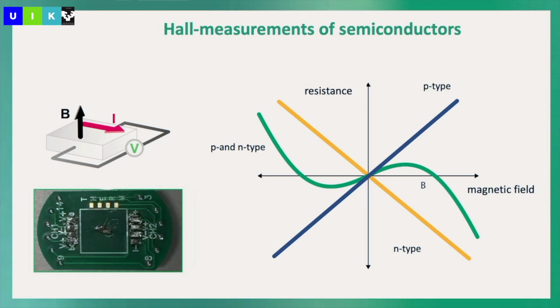This is what you can distinguish even in semiconductors, very typical. Then you can see what the charge carrier concentration is and so on from this measurement. But sometimes you also see wiggles here, and you might think it's impurities, but in these materials we very often see very nice quantum oscillations, from which we can even draw a conclusion by a simple transport measurement about what the electronic structure looks like. So we don't even need ARPES or photoemission or some complicated measurements, because very often we get this information. And it's amazing, before I never did this, but now, since there's topology, all my crystals suddenly have this quantum oscillation, which is very nice, because we get much more information out.